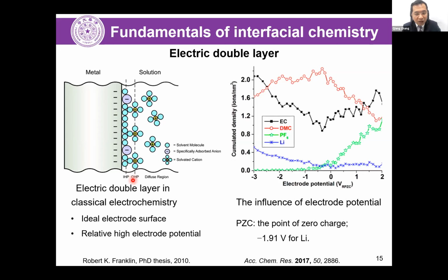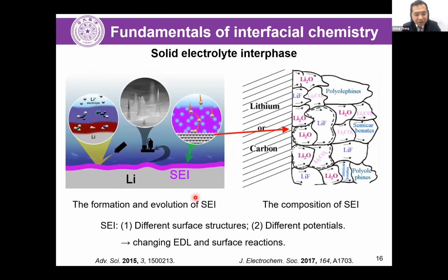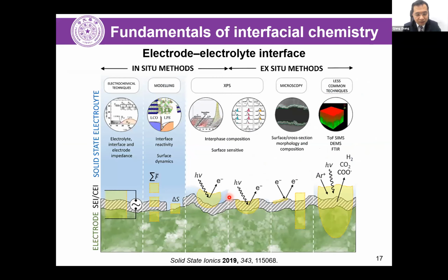So based on this consideration, we try to probe the electric double layer at the interface, and we try to understand what's happening here. In fact, there are always solid byproducts on the surface. The solid products consist of many oxides, fluorides, carbonates and also some organic lithium salts on the surface. They prefer to form a film on the surface. They will expand or shrink based on the plating and stripping of the lithium metal anodes. In fact, if you check the composition of the anode SEI carefully, it is found that the composition and its structure highly depend on the degree of discharge or charge of the battery. So there are some emerging characterization methods presented in this figure. It is found that a lot of advanced characterization can be employed here.